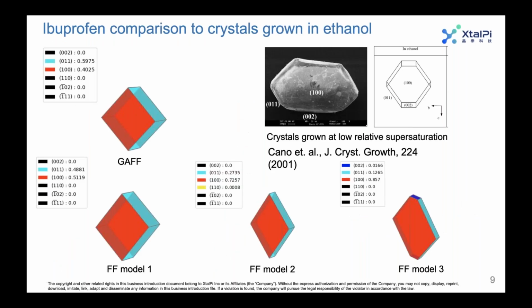In the previous table, I showed you 4 force fields. 1 was an out-of-the-box force field. 3 were tailor-made force fields incorporating different training parameters. I'll show you how they perform on a test system of ibuprofen in ethanol. In the right-hand corner, I have an image here of an ibuprofen crystal that was grown in ethanol. And this cartoon diagram here is the morphology of ibuprofen grown in ethanol based on the measured experimental growth rate.